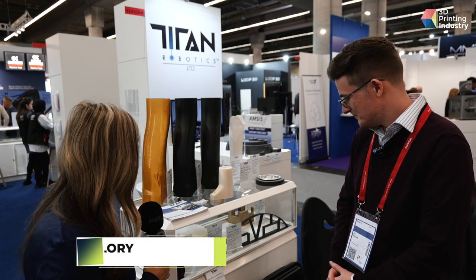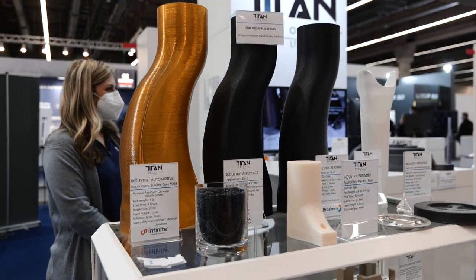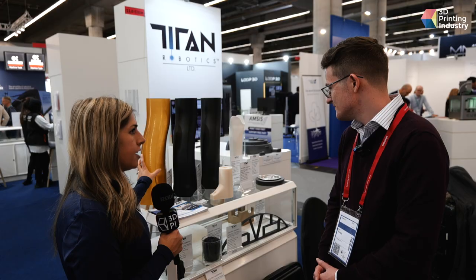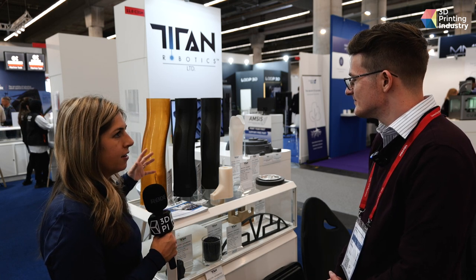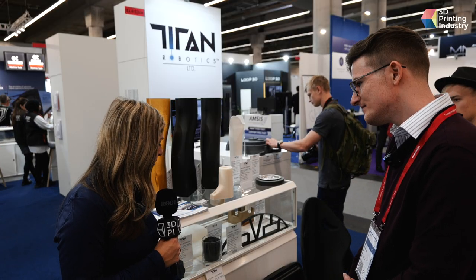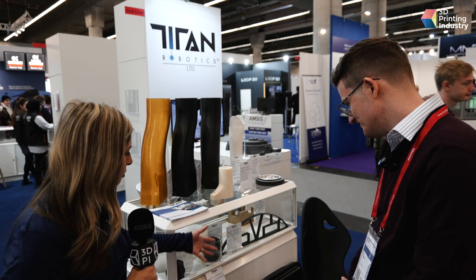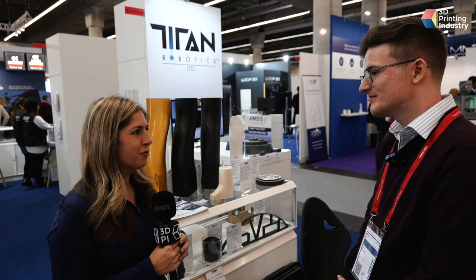We brought some sample parts here for the US Pavilion. Some of the parts on display are end-use production parts — ducts made out of different materials. This is AMSIS 120, a soluble material often used for soluble support because it dissolves in warm water, but this application is actually a soluble core — you lay up carbon fiber around it and dissolve it away. This is carbon fiber Ultem, this is carbon fiber polypropylene, and we also have a glass fiber polycarbonate thermoforming mold — printed and used directly in a thermoforming process.